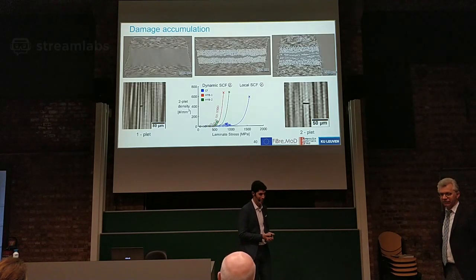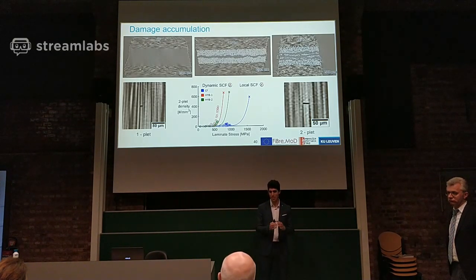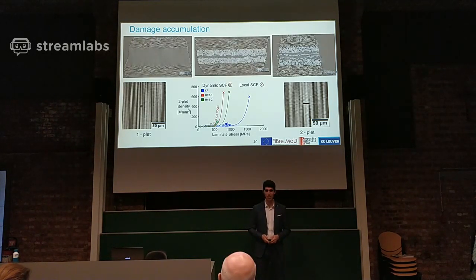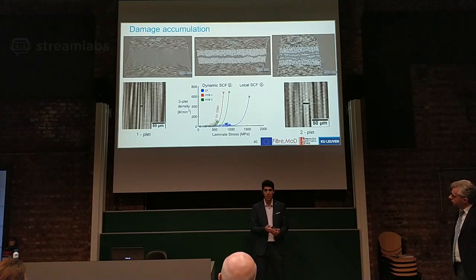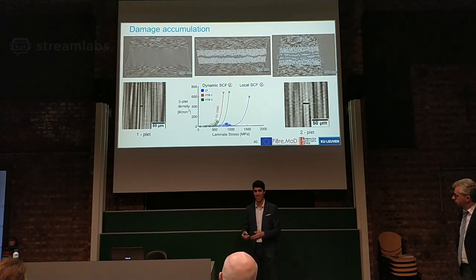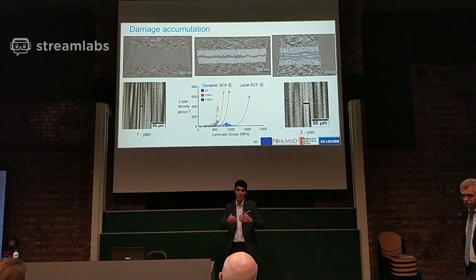Yes. So the importance is, how reliable is this average strength value that we are using here? Exactly. Is it 16 worth of reliable, or only 14? I think it's about safety. But in composites, the fact that the fiber has a different modulus, actually I cannot recall now, but one of them will yield a higher or different strength, but still a gradual process. So fibers will still break gradually and accumulate. If you have a lower modulus, they will accumulate from an earlier stage compared to a higher modulus. So I think the views are a bit different in composite Weibull modulus or fiber Weibull modulus, because one influences the strength of the composite, the other one is already the scatter of the composite.